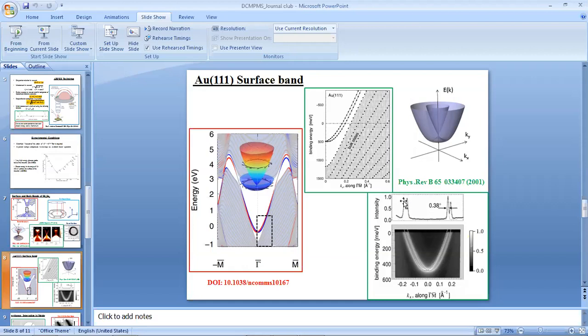Here they have normalized this graph, but you actually get the count. Maybe it is 20,000 or 30,000 or 50,000. It depends on how long you have taken the spectrum. If you want to make it much sharper, then you perform this experiment for 2-3 hours. Then you will see that the electron counts will be in lakhs or millions, and it would be very sharp.